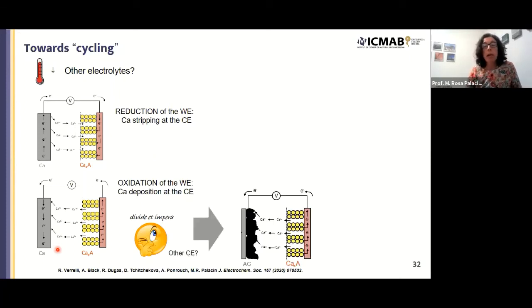And we used activated carbon as counter electrode. This is an electrode operating via a capacitive redox mechanism. So the main issue here is that the capacity is very small. So you need to use a huge excess of negative electrode. So the balancing of the cell is tricky.